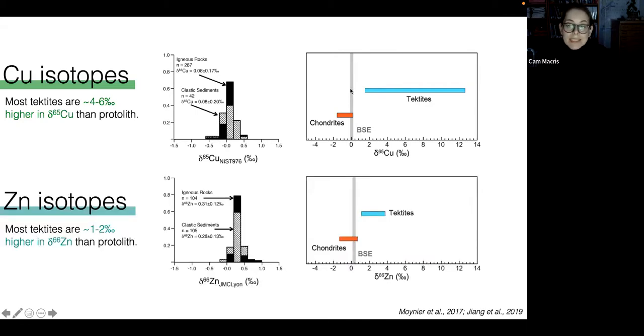If we look at the same data for zinc, we see that sediments are around 0.28 per mil in delta 66 zinc, which is again represented in this plot as the gray bar for bulk silicate earth. And we can see that tektites range from about 1 to 4 per mil, and that they are about 1 to 2 per mil higher in delta 66 zinc than sediments or the protolith.